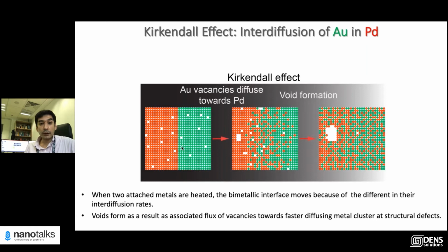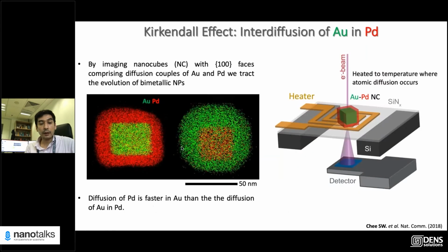And we set out to explore this. We wanted to make an alloy nanoparticle and see what happens. So we prepared two sets of nanoparticles, or diffusion couples. In one of them, gold was in the center and palladium was on the surface, and then we reversed the geometry, just to look at what happens. And this is the basic experimental schematic.